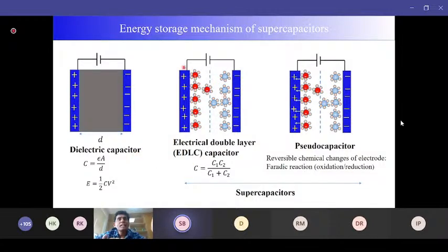But the important thing here is that instead of one capacitor, you have two capacitors, one on the anode side and one on the cathode side. They are connected in series, so the overall capacitance is just the series combination of the two capacitors, C1 C2 by C1 plus C2. In this way, you can increase the capacitance by a significant amount. This is a very high amount, orders of magnitude higher than dielectric capacitors.